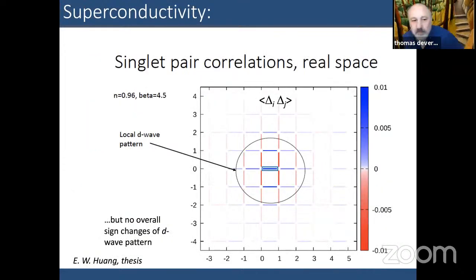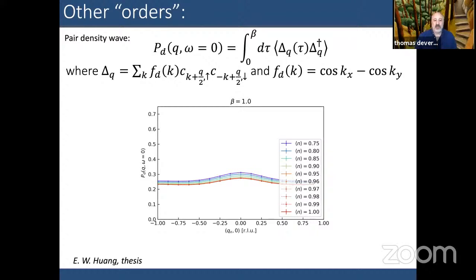First, let me show you the pair field correlations, delta i, delta j, in real space. So you can see, this is from quantum Monte Carlo data, that you do have a very nice local D wave pattern going from this reference bond here. And then it decays. We don't have truly long range order, but then you have to look over in these corners to see whether or not this pattern inverts or flips or has a sign change. And at least for the level of data that we have, we don't see any overall sign change of the D wave pattern. And so we can put that in momentum space by looking at this Fourier transform.